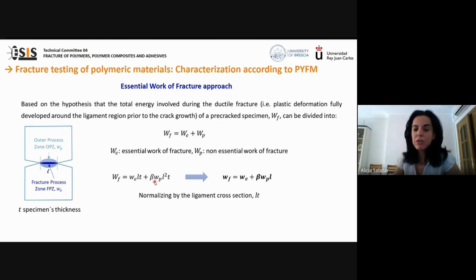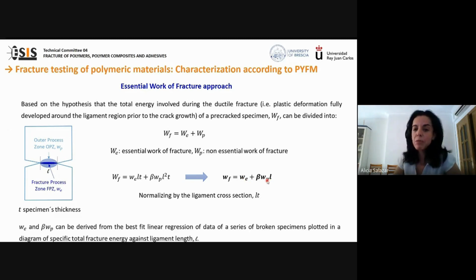Normalizing by the ligament cross section, we obtain the following expression, where the fracture parameters, the essential work of fracture and the non-essential work of fracture, can be obtained from the best fit linear regression of data of a series of broken specimens plotted in a diagram of the specific total fracture energy versus the ligament length, as shown in the next slide. I don't want to skip this, that for film characterization, normally a double-edge notch tension configuration is employed, as shown in this plot.